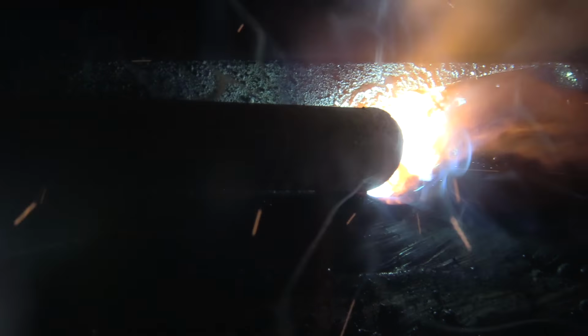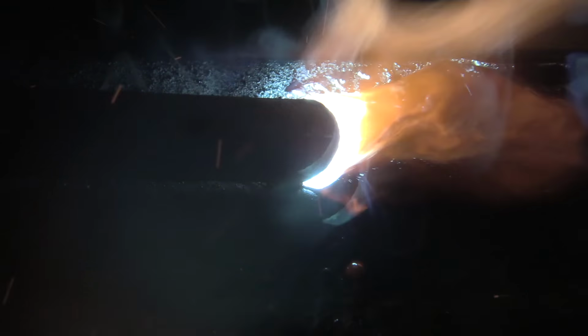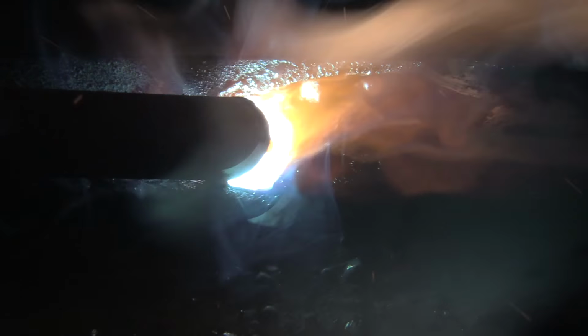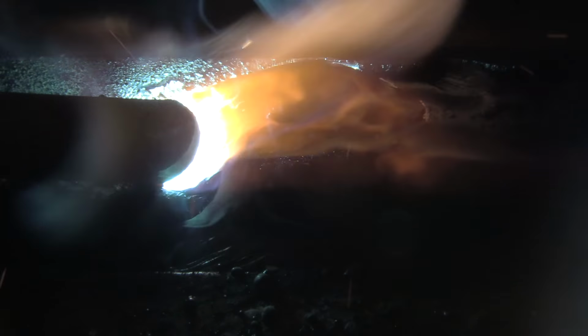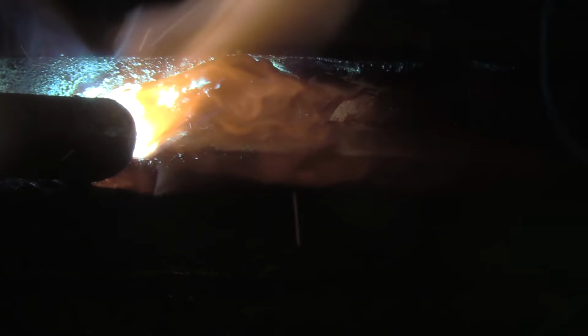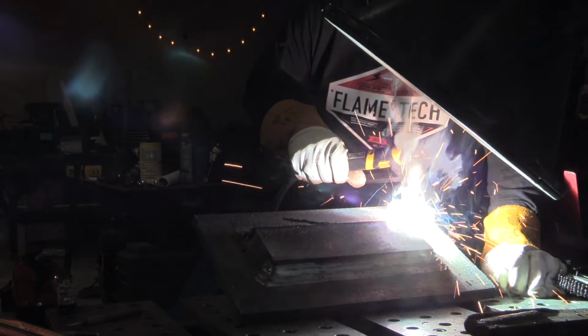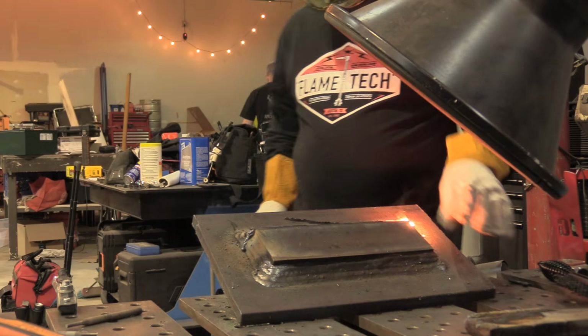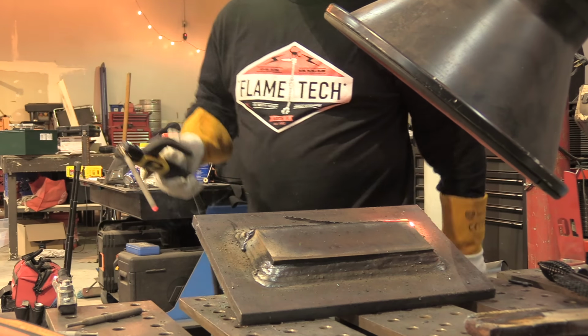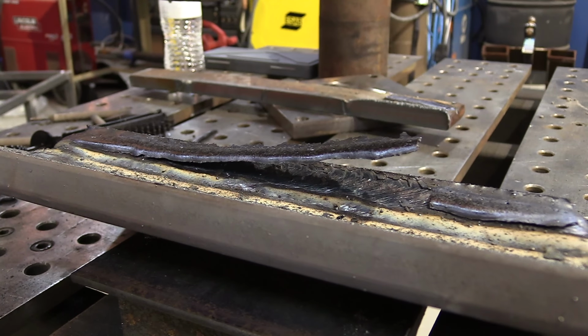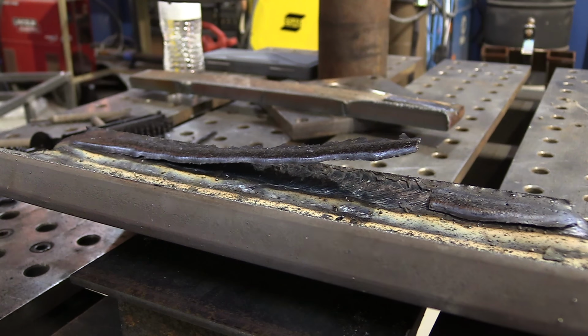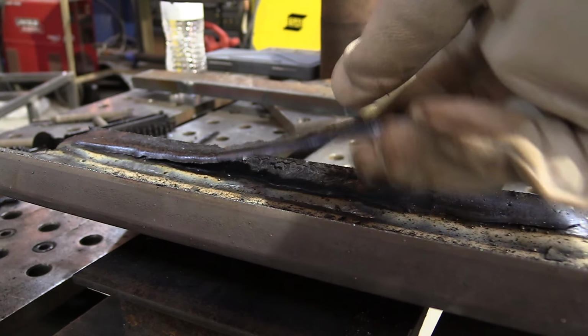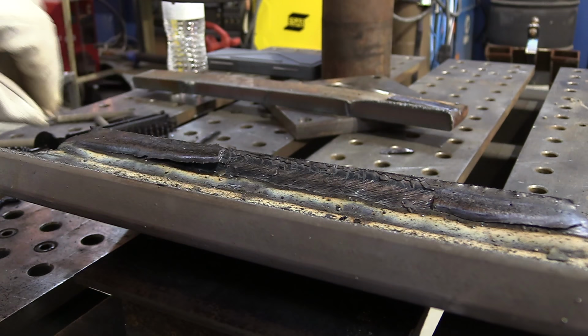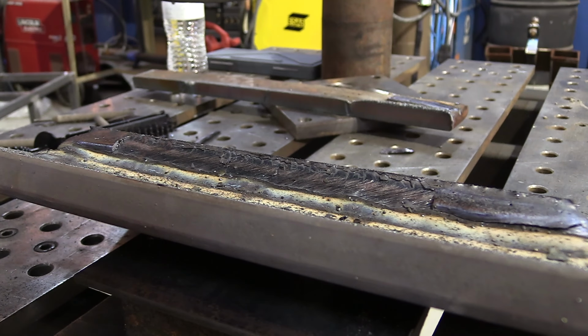This puddle is so hot that while I'm watching just the immediate area around that electrode, it's hanging back there so far and just chewing away the corner. So when you're welding near an edge, that's a really hot puddle, and it can chew off the edge and leave it really choppy with some undercut there. With the slow cooling and the big hot puddle, it'll make a smooth bead, and you'll get peelers every now and then like this. I even got this one to peel, even though I have that choppy edge with the undercut.